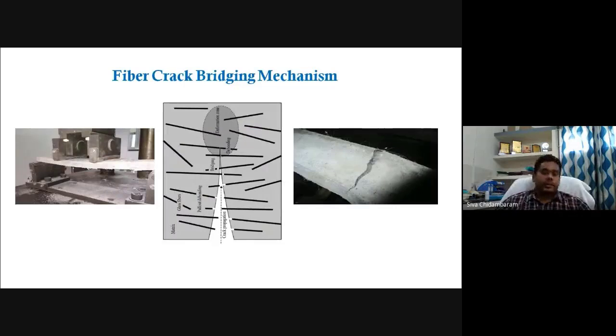When we use these kinds of fibers in our concrete, that will bridge the cracks at multiple levels. It is not a single point, it is at multiple levels, because they are randomly distributed, randomly oriented fibers. Micro level, nano level, macro level, all the cracks will be bridged by the fibers. It will try to transport the stress from one point to another point. So this is called the fiber crack bridging mechanism.